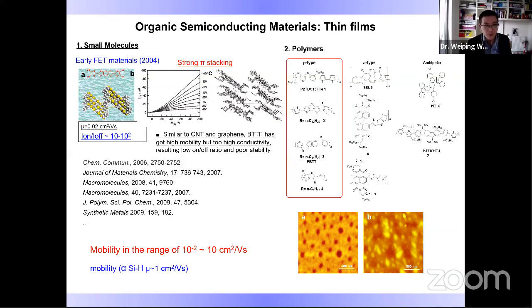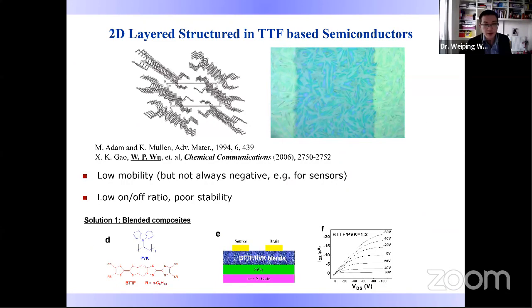For instance, we have found a very interesting class of extended TTF molecule, which has been synthesized. As you can see from this slide, it's called BTTF. It's a kind of 2TTF molecular structure, coupled with a benzene. This structure has very strong pi-pi interactions, and this small molecule tends to crystallize into crystals. So you can see these fine crystal ribbons at the channel between the two gold electrodes.